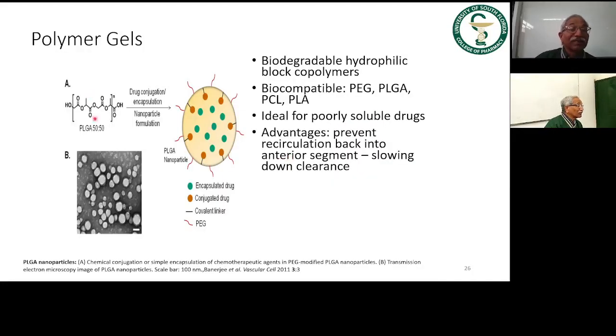So polymer gels are normally, this is like a PLGA 50-50. So you put PLGA nanoparticles, you incorporate your drug inside, the green particles are the encapsulated drug, and then they look like this under a transmission electron microscope. So these are PLGA nanoparticles. Now what you do is you create a PLGA nanoparticle and then incorporate those nanoparticles in another polymer which is hydrophobic, so that it remains in the eye as a depot for a longer time. And that's what we try to do.